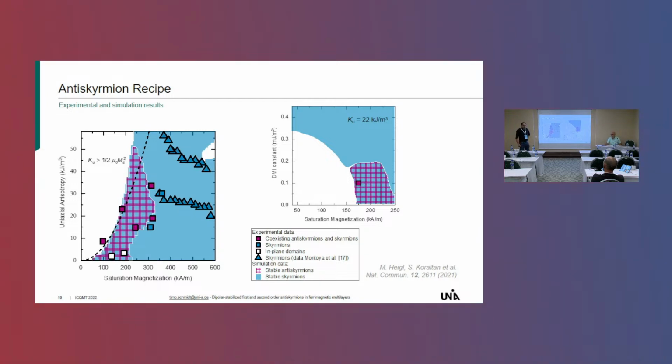Yeah, I'm really not that sure about that. I don't think so, but there is a strong induced moment on the iridium. So it definitely reduces the saturation magnetization, because we had films without them and with some iridium layers, and the saturation magnetization goes down. What the reason for this is, I'm not that sure, but basically we don't have DMI as we expected. I hope that somehow answers it.